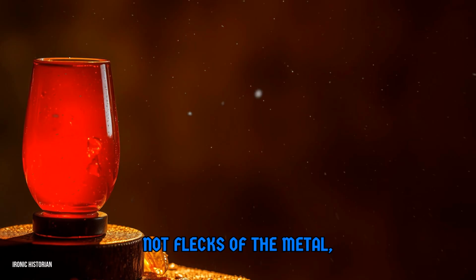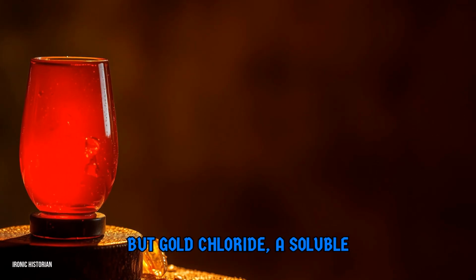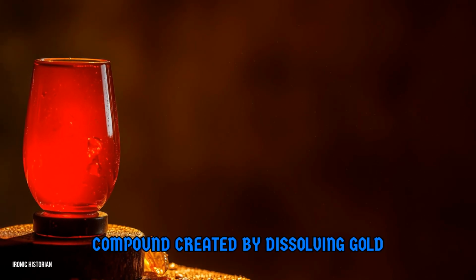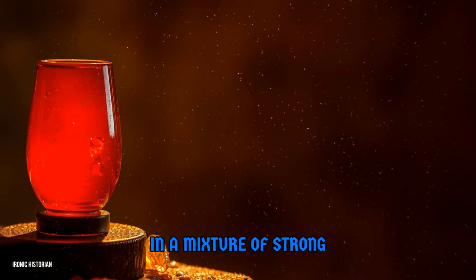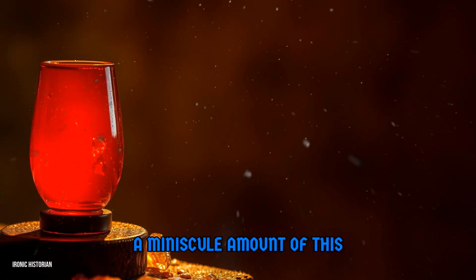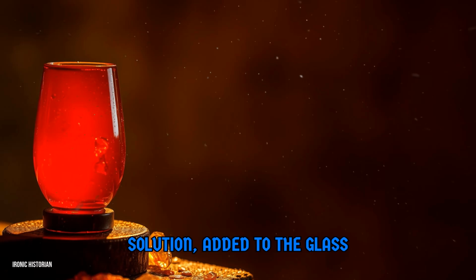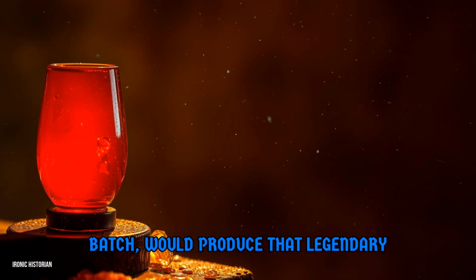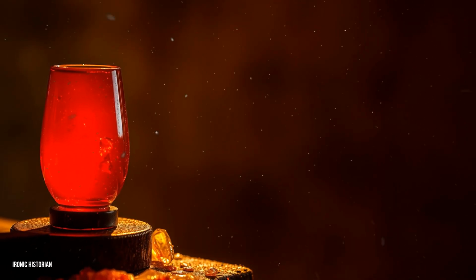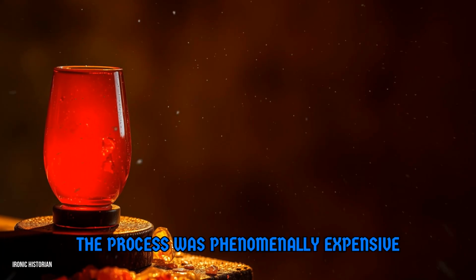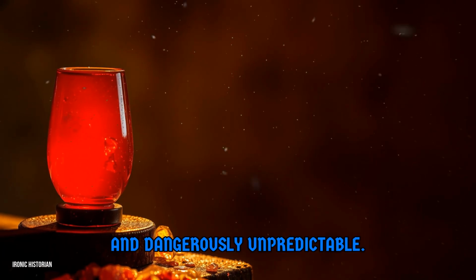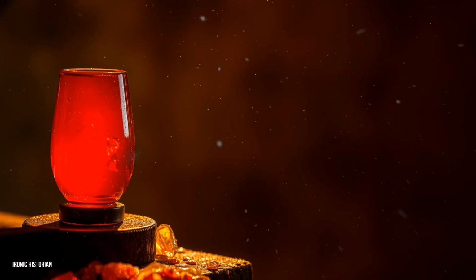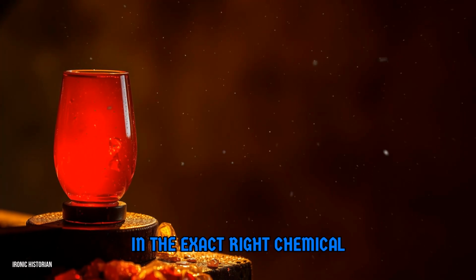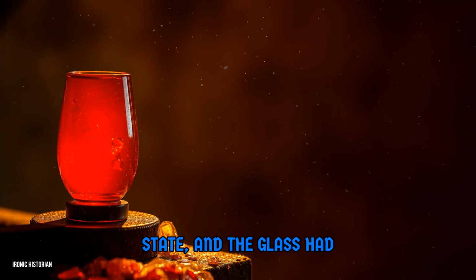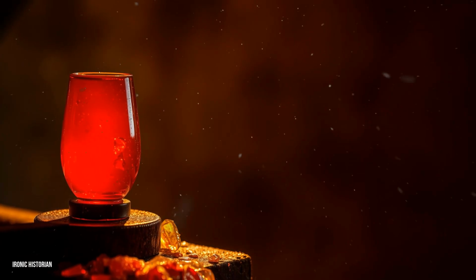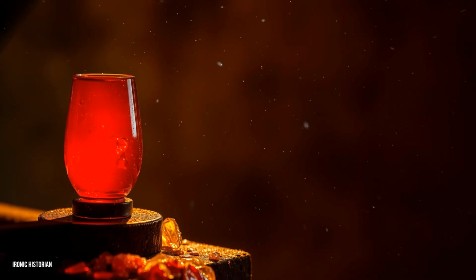Not flecks of the metal, but gold chloride, a soluble compound created by dissolving gold in a mixture of strong acids. A minuscule amount of this solution, added to the glass batch, would produce that legendary red. The process was phenomenally expensive and dangerously unpredictable. The gold had to be in the exact right chemical state, and the glass had to be reheated in a specific way to develop the color.